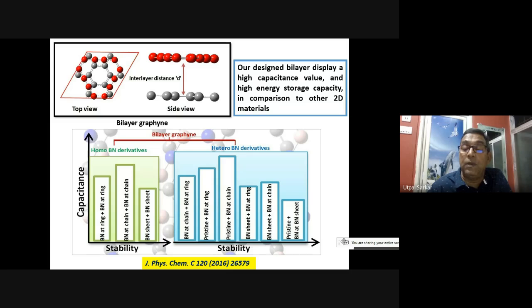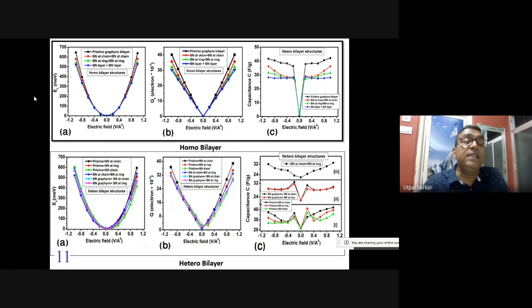So this is the most stable one. However, for the heterobilayer, pristine and BN sheet is the most stable one, and this one is the least stable among these. This is the energy storage of this capacitor. This is the charge storage, and this is the capacitance for different electric fields. Okay, so what we have seen is that the energy storing capacity for pristine graphene is larger than the other one. The least one is the BN and BN layer.